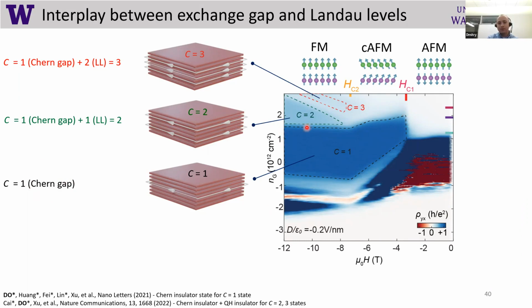So it occupies a large region of the phase diagram, and it's related to the fact that we inverted our band structure with magnetism in the system. So this is a magnetic topological insulator Chern gap. But then when we start increasing our gate voltage, so moving from the gap up, getting into the conduction band, we also get Chern number 2 and Chern number 3.